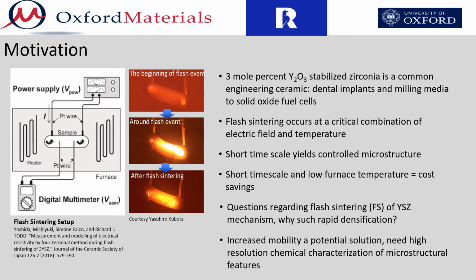One potential method for increased sintering efficiency is flash sintering. Flash sintering occurs at a critical combination of electric field and temperature. In practice, a specimen is placed in a furnace, heated to a temperature much lower than that required for conventional sintering, and an electrical current is applied across the specimen length. Flash sintering then occurs in a matter of seconds as opposed to a matter of hours when using conventional sintering.